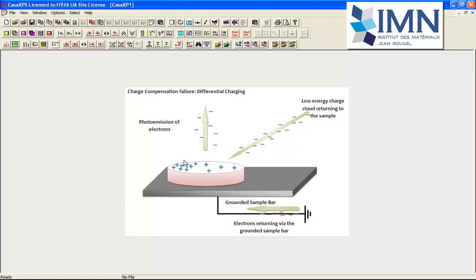The reason this peak is moving is because when we consider the sample that is differentially charging, for some reason the neutralization or the lack of neutralization is allowing a buildup of charge in one part of the sample that is different from another. Because the potential is different at these two points, we end up with a shift in any photoemission peak in terms of its kinetic energy that depends on the amount of charge in each one of these zones.